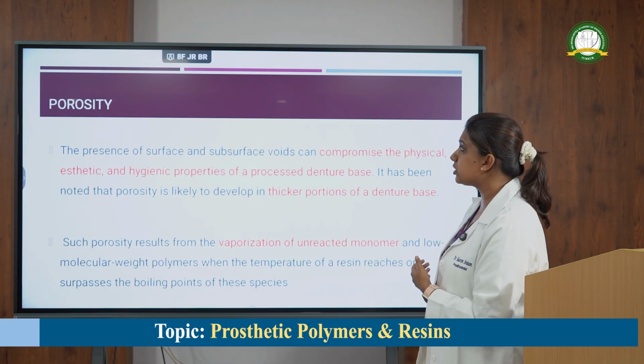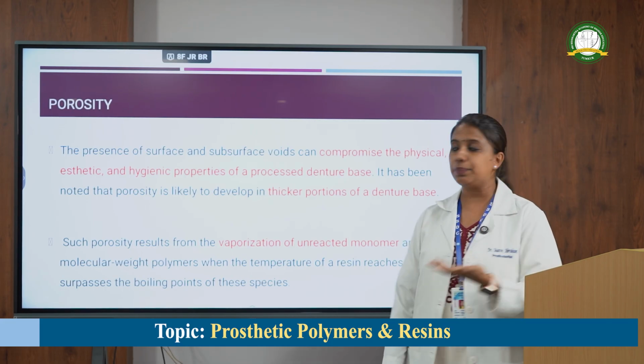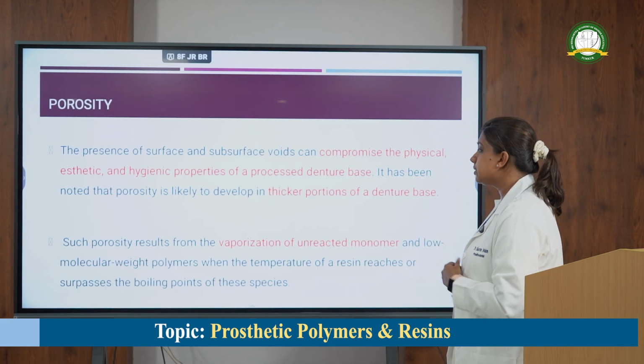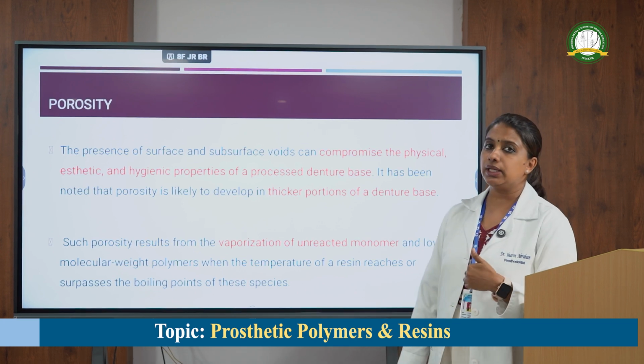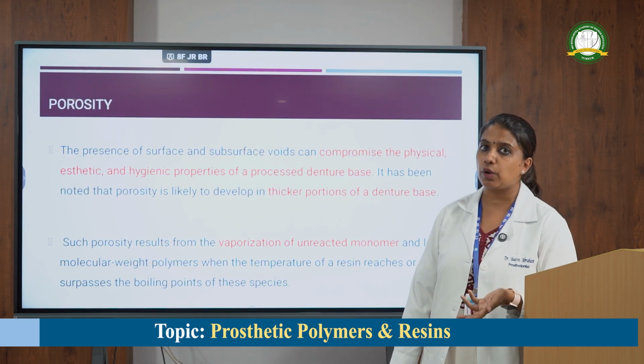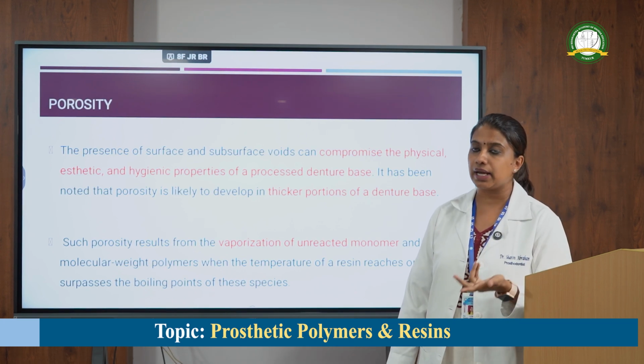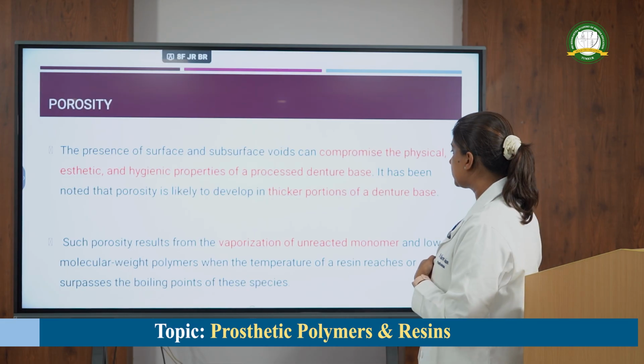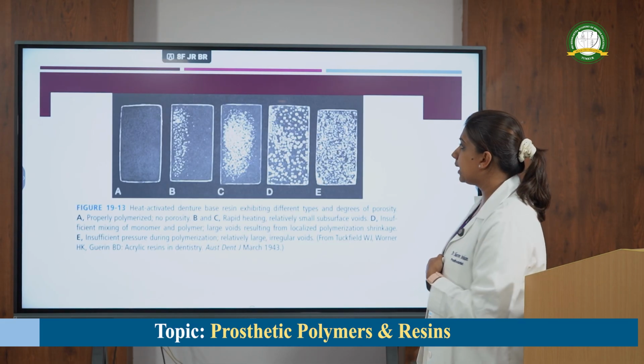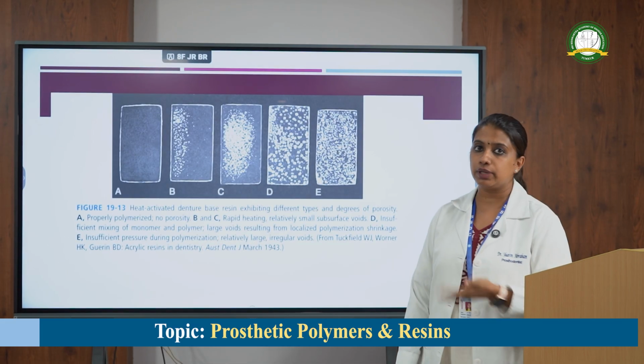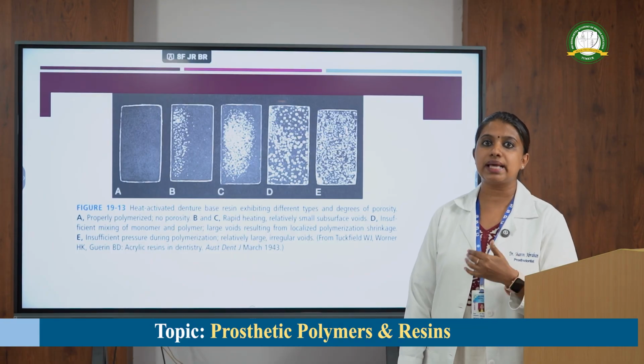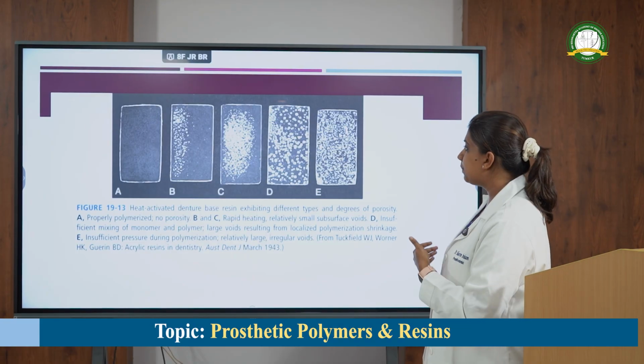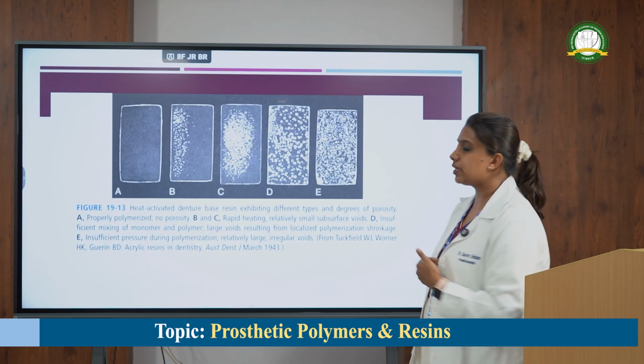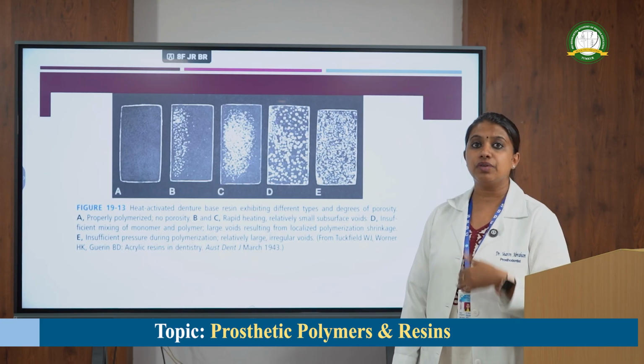Now, how does porosity mainly occur? Because of vaporization of the unreacted monomer. Whenever there is an unreacted monomer present after polymerization, and it gets vaporized, it leads to porosities. You can see in picture A, there is absolutely no porosity because the polymerization process was complete. Whereas in pictures B and C, subsurface porosities can be seen because of rapid heating.